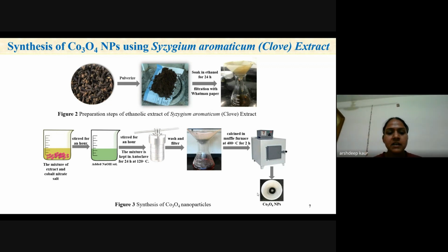For the synthesis, first, the mixture of the extract and the cobalt nitrate salt was used. These both are mixed and stirred for an hour. Then for the pH setting, we have used the NaOH solution. After adding NaOH solution and setting the pH at 9, we have stirred for an hour. The mixture then kept in an autoclave for 24 hours at 120 degrees Celsius. After cooling down the autoclave, we have washed and filtered the obtained precipitates. The obtained precipitates then dried and calcined in muffle furnace at 400 degrees Celsius for 2 hours. Then we have obtained the black color precipitates.